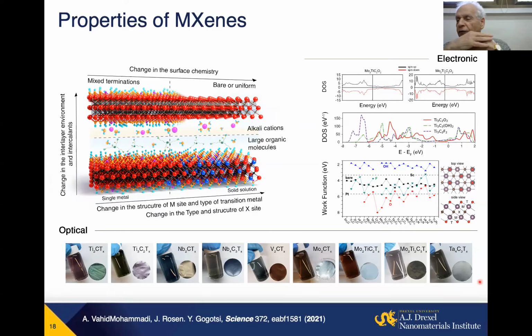Anybody has tried to do twistronics with these layers? Yes, there was a paper published 2 or 3 days ago. Can check, and this is the only work I know. And of course, after graphene and dichalcogenides, everyone is trying here. So they showed, actually, they did not take in a controlled way and rotate crystals. They simply went to these delaminated flakes and looked at basically 2-layer flakes which were randomly assembled, and the ones that were in registry and the ones that were slightly rotated showed different properties. But the paper, as I mentioned, was published earlier this week, I think on Monday. So I still need to read and digest it here. It was in ACS Applied Materials and Interfaces.